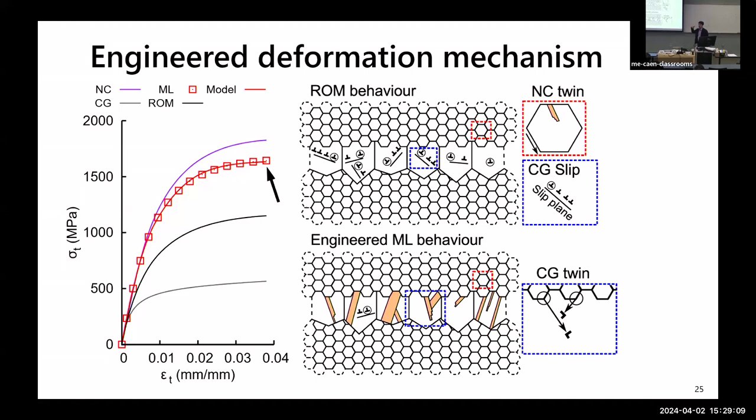However, that behavior breaks down when the thickness of the coarse grain layer is close to the crystal size, and you do see this crosstalk. And what we can do through a very simple Kocks-Mecking-like model, which I don't have time to get into, a work hardening model that's used to predict the flow stress of materials and can take into account twinning behaviors and also dislocation-dislocation interactions, is actually recapture the true experimental behavior by adjusting our work hardening model to accept this information. So that's the major outcome of that area.